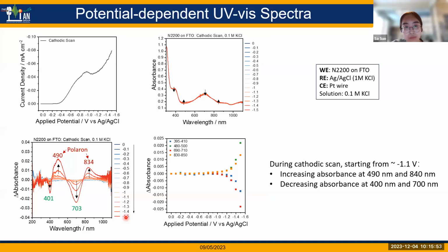So we also did a similar experiment, but the first experiment I will show is done in water. So the solution is 0.1 molar KCl, and the working electrode is N2200 on FTO. The reference in water solution is the silver chloride electrode, and the counter electrode is just platinum wire. So if we look at the current data, we can see that during the cathodic scan, there is a reduction peak at around negative 0.9 volts.